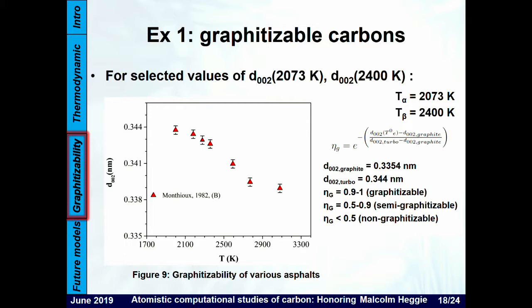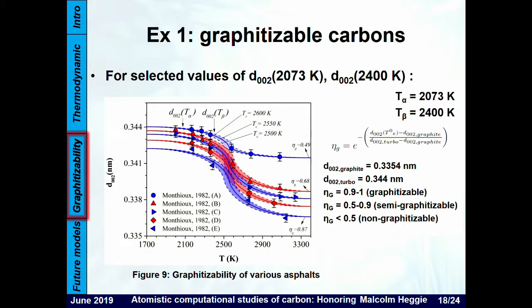As you can see here, you have the graphitizability of various asphalts. This is the experimental result, and you select the value of D002 at the T alpha temperature and D002 at the T beta temperature, and you get this prediction. If you change the value of Tc, you get this kind of lines, and you can repeat the exercise for various kinds of asphalts to see that the spectrum of graphitizability is more or less acceptably represented by the present model.